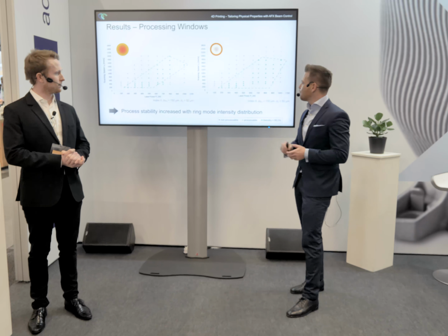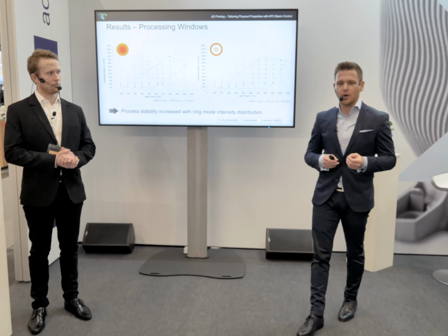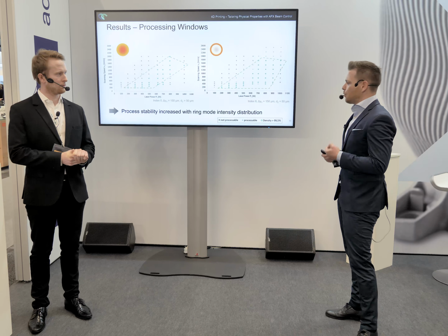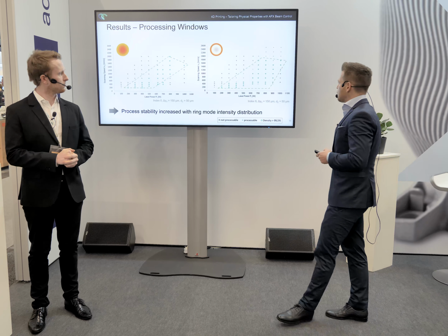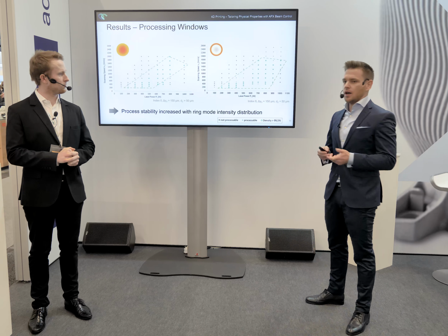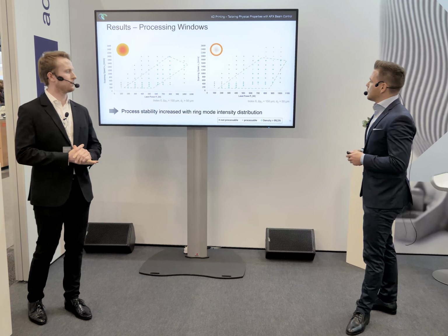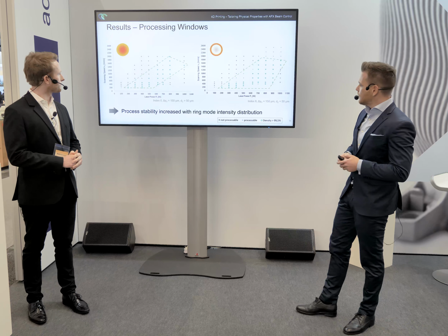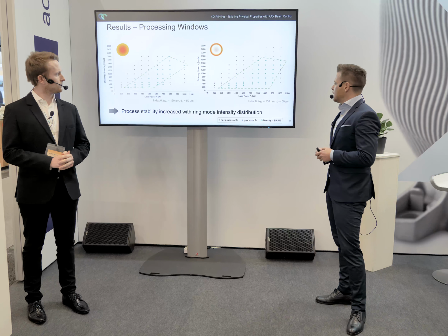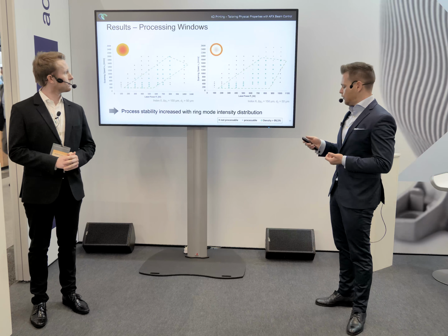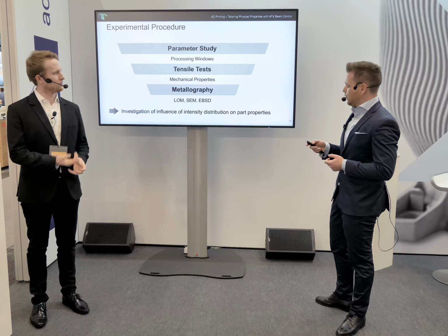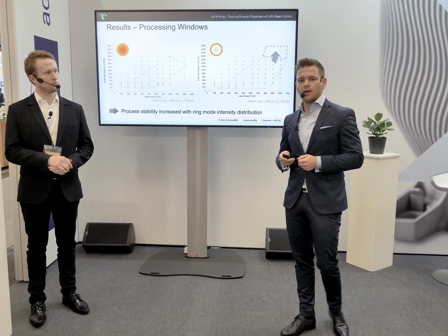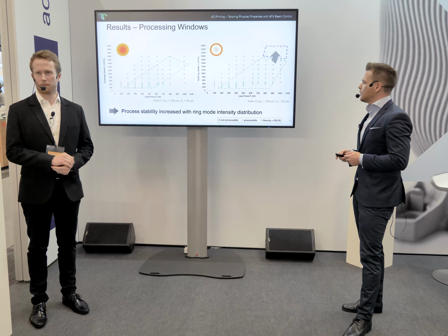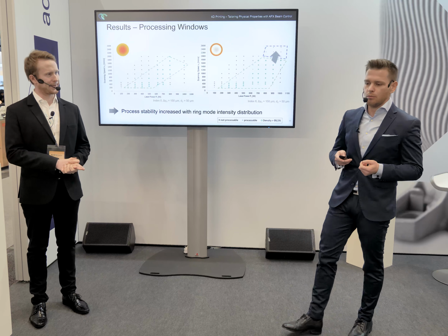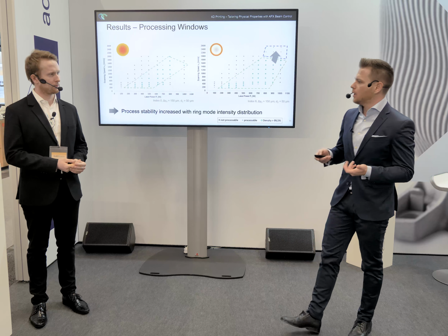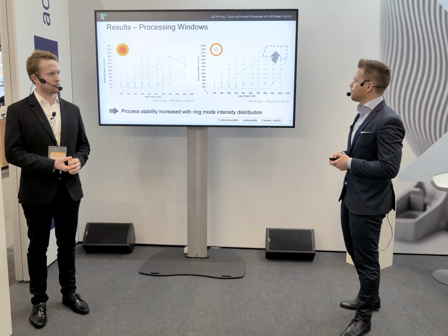As you may see, first of all, the black X's are parts which were not processable. The blue ones were processable, and those with a green circle are with a density higher than 99.5. And as you may see here, the processing window for index 6 is a little broader, especially in the region of higher energy density. And first further experiments revealed that, even at higher power and higher scan speed, there were parts processable, leading to the assumption that increased process stability may be with the index 6.